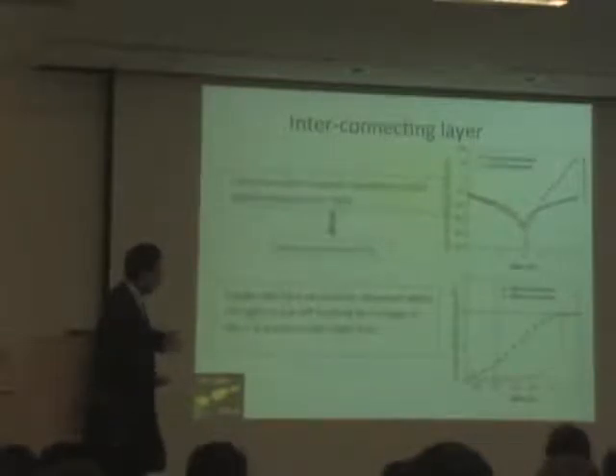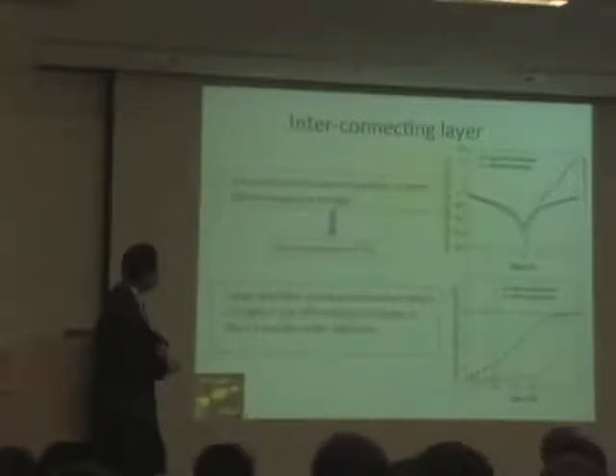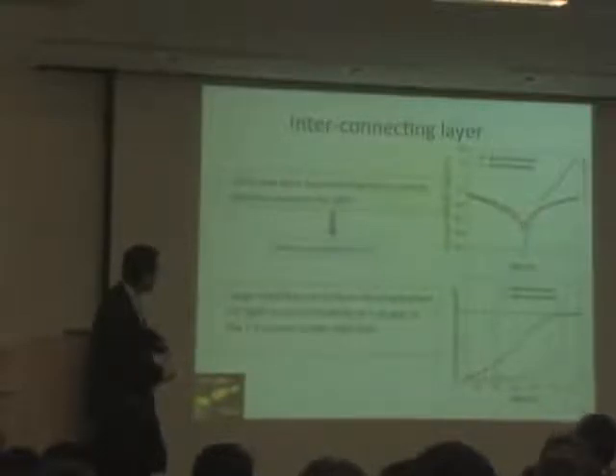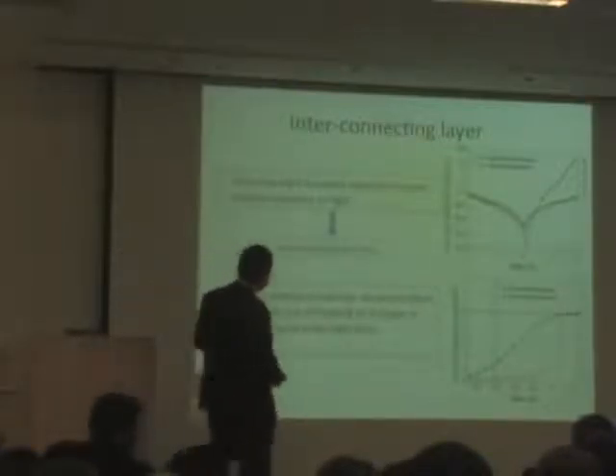Okay, so the interconnecting layer. I talked about TiO2 not being easy to handle. I'd like to tell you why. The TiO2 is a photoconductor. So if you just build a solar cell, this is a dark curve. And the student might measure the IV curve, walk away and say this idea doesn't work. But I want you to be patient, because you need a little bit of UV light as a trigger to have photoconductivity. You can see the IV curve without light soaking and with light soaking. You get a very nice IV curve. So that's the trick. I want you to be careful, particularly graduate students: if an experiment doesn't work, go get a cup of coffee, come back, and your experiment might work. You need to be patient and give it a little bit of time, so this thing will start to work.